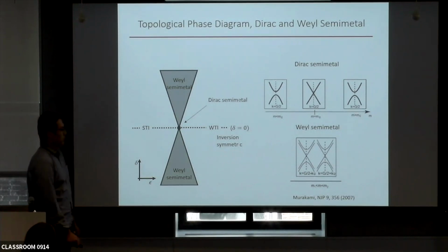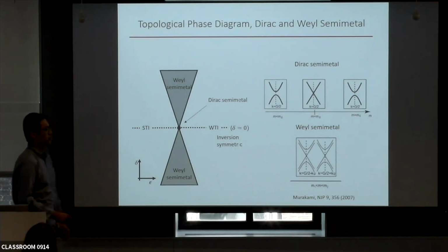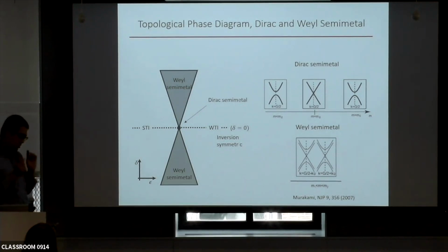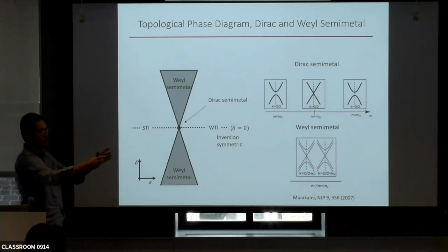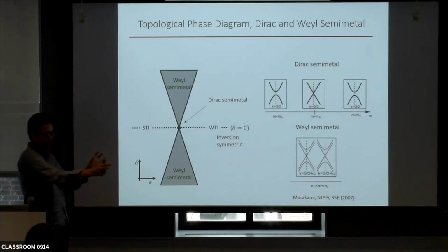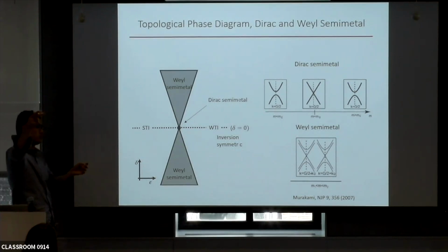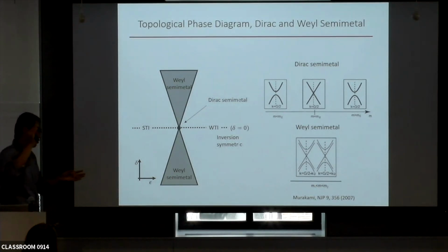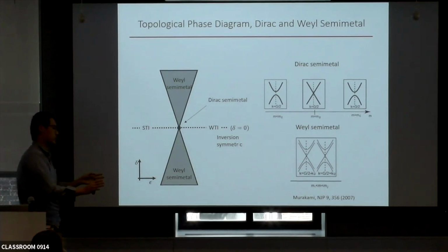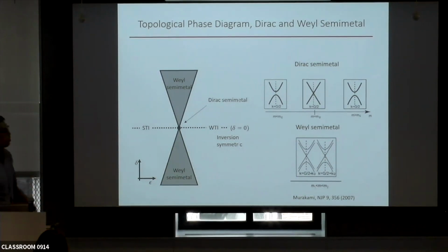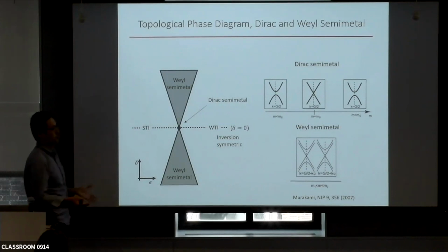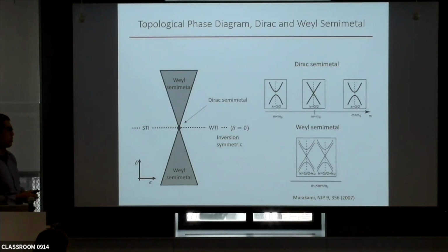Right. We tried to do that, and the attempt failed. The way we do that is that you can measure the crystal without applying any strain, measuring R versus T, for example. When you put it on the device, because the device has all kinds of thermal contraction, you'll naturally strain the crystal. But because now we can tune the strain, we can tune it back to the zero strain state by referring to the zero-strain resistance versus temperature measurement. You can do that all the way down to 60 Kelvin, but somehow below 60 Kelvin, we always lost track. The only thing I can say is that we can give an upper bound of the gap, maybe around 20 millivolts. It's an upper bound.